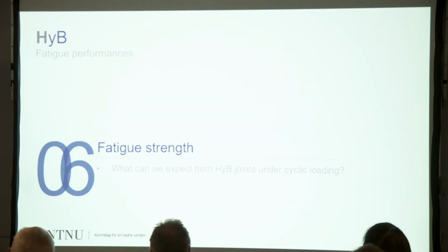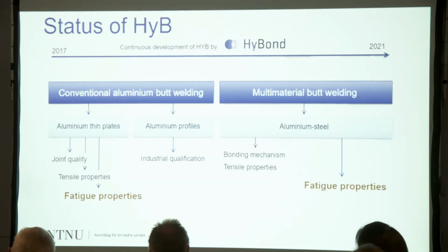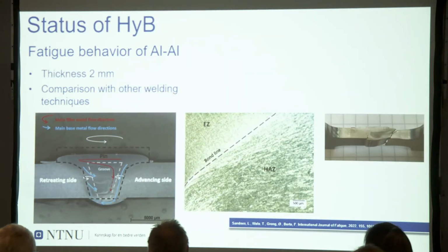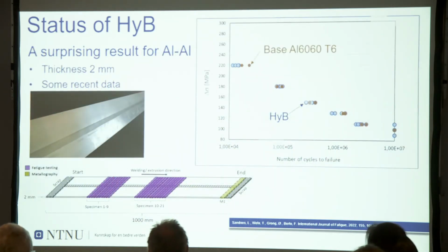Now we go to the focus of this talk, and this is the fatigue strength of these joints. So we made a full classification, or a full analysis, of these bonded joints. I will not report everything here, but going to the fatigue properties, we studied the fatigue behavior of aluminum with thickness 2 millimeters. What was quite interesting for us is that in this graph you can see that the base material and the HyB have almost the same fatigue life. So this means that the fact that we have a bonding line is not really affecting or reducing the fatigue life in comparison with the base material, which is quite impressive, and we will understand later why.